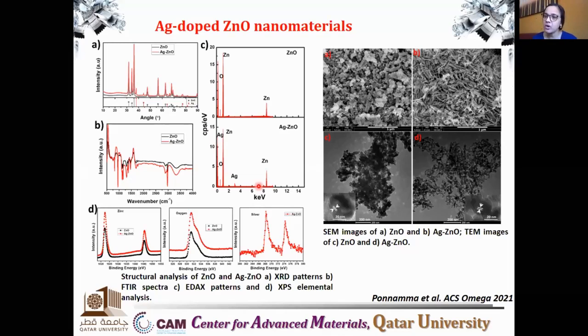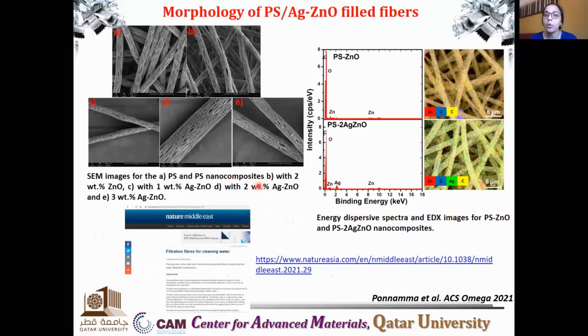Why are we using zinc oxide and silver doped zinc oxide in particular? You have to understand that zinc oxide is a semiconductor and has an amazing property of photocatalysis. So here our aim was to make the membrane multifunctional. With zinc oxide, we can target the photocatalytic property, and with silver, we can target the antibacterial performance. And now comes the highlight of the research, the porous fibers. This was also done by electrospinning, but not the normal electrospinning. It was non-solvent induced phase separation assisted electrospinning.